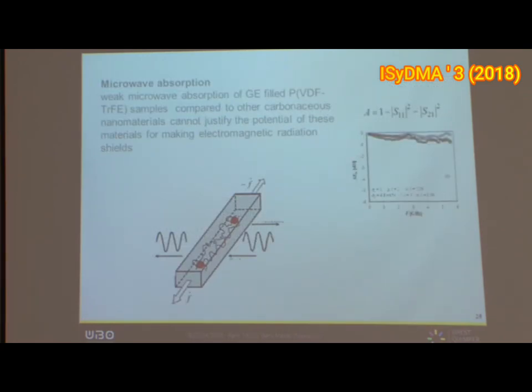If you look at applications such as microwave absorption, this kind of sample is not very good. I'll show you a result of absorption as a function of frequency. Here's the experiment we do: we exert force in some direction with different elongation ratios, input some power, measure the reflected power, and calculate what has been absorbed in the bulk of the material.